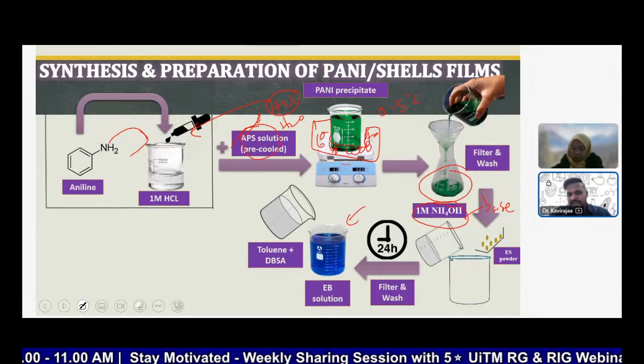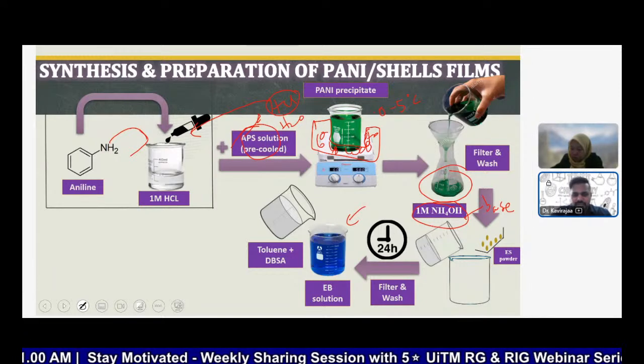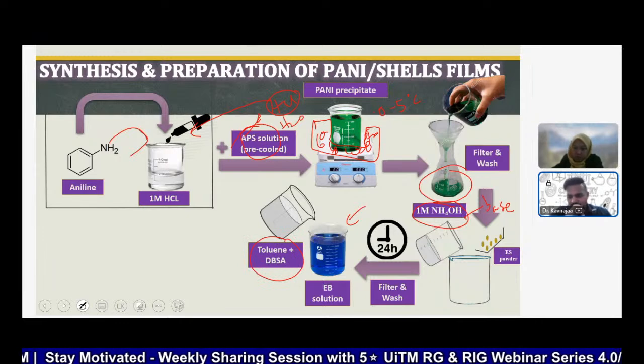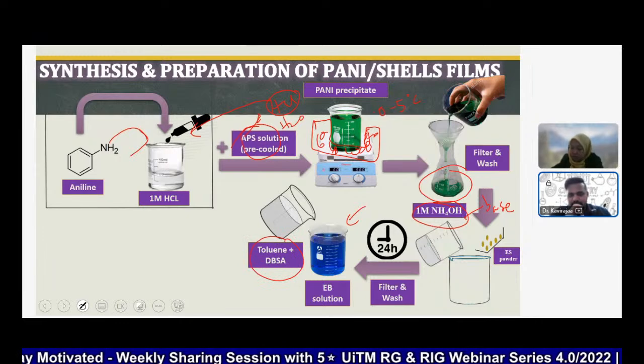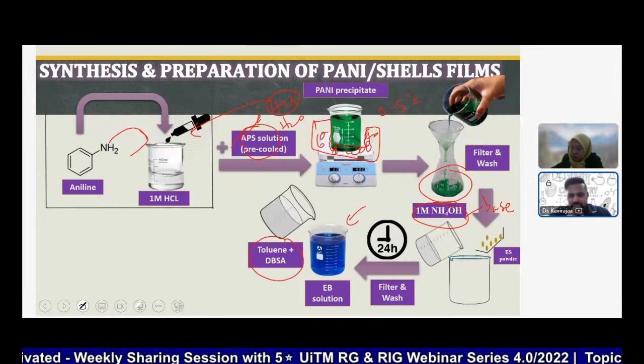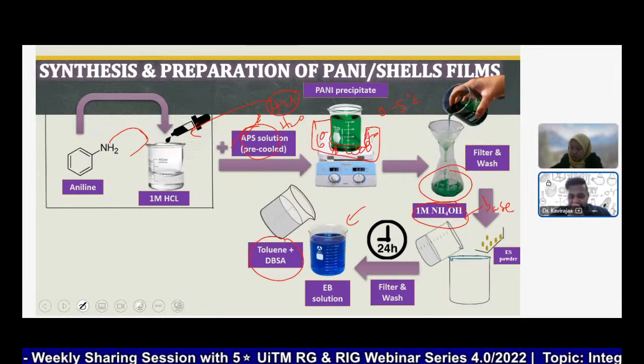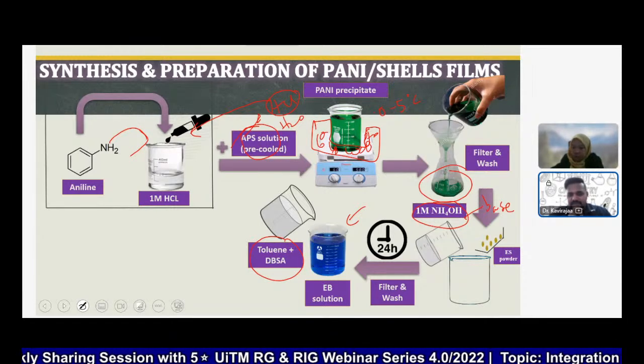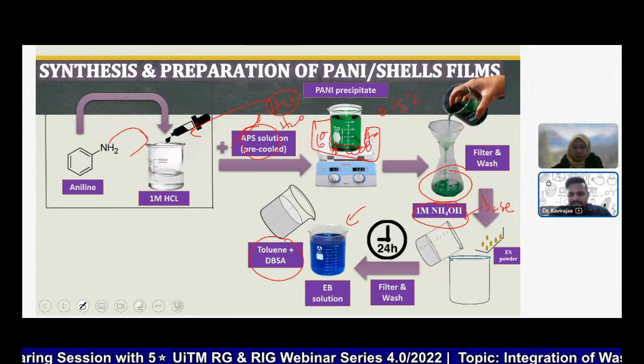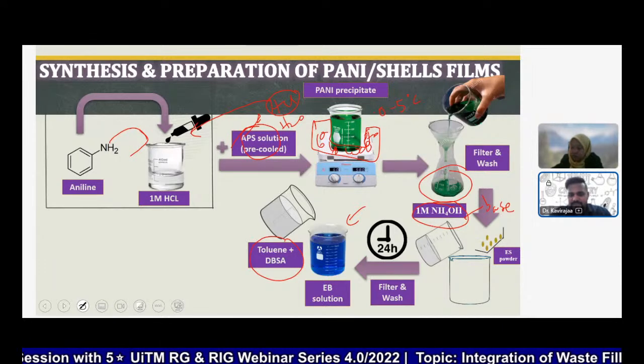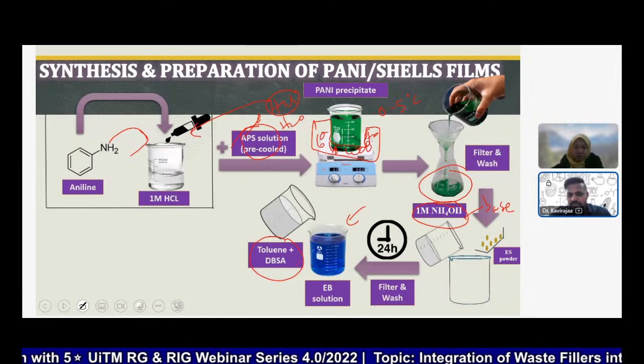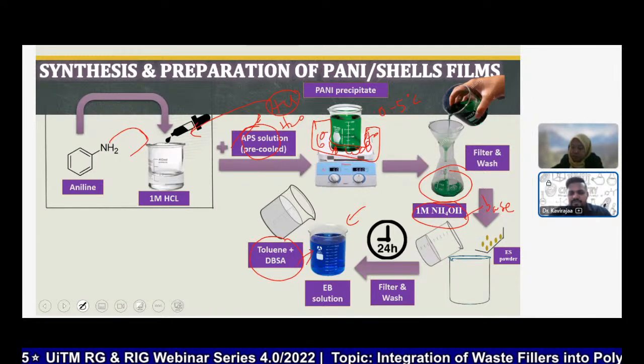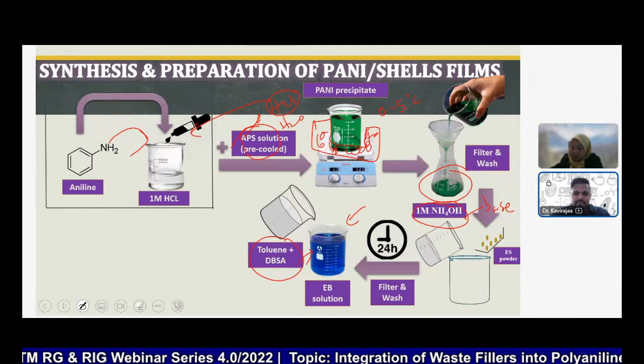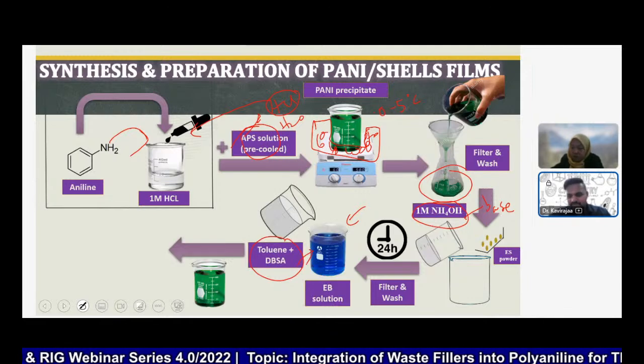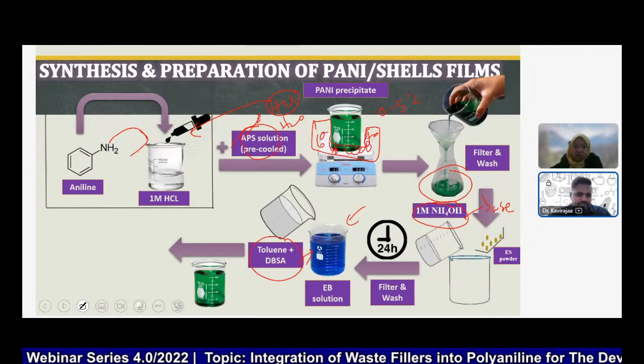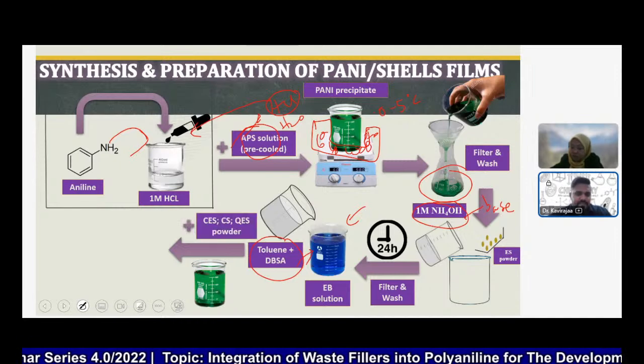Okay, this one we will filter, and then only we will add toluene as a solvent and DBSA, but toluene is toxic, so nowadays we no longer use toluene. We use the DBSA, dodecyl benzene sulfonic acid, which is a surfactant, an acidic surfactant. This acidic surfactant will behave as a proton donor. That means it will make the polarons available again in the polyaniline. So we will get back a green color solution. That green color solution, we will filter it, wash it, and then